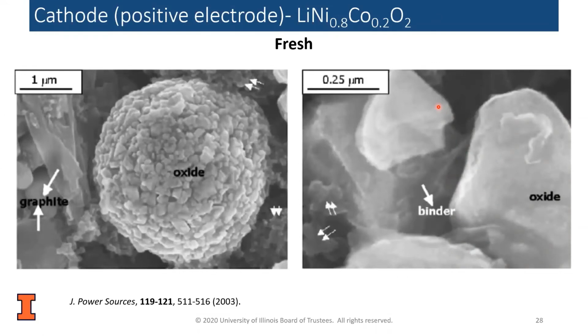So what does the oxide particle look like? You'll see that the oxide has a large secondary particle that's made up of a number of smaller primary particles. It is engineered like this on purpose, so that the oxide particle has a large surface area, so that we can get a lot of lithium intercalating in and out of the oxide. You could actually go to Sigma Aldrich and buy this oxide, NCO, and make a battery with it.